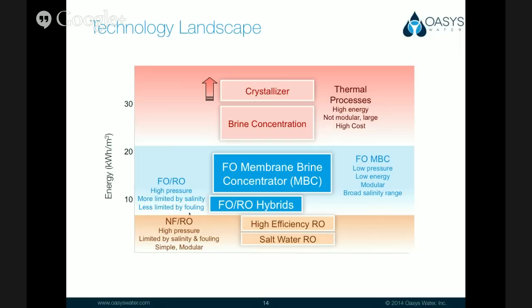I'll also note that in terms of energy, what I show here is actually for pretty ideal circumstances in many evaporators. Now, often batch brine concentrating evaporators will typically be more in the range of, say, 30 to 50, and crystallizers could be as much as 100 kilowatt hours per cubic meter.